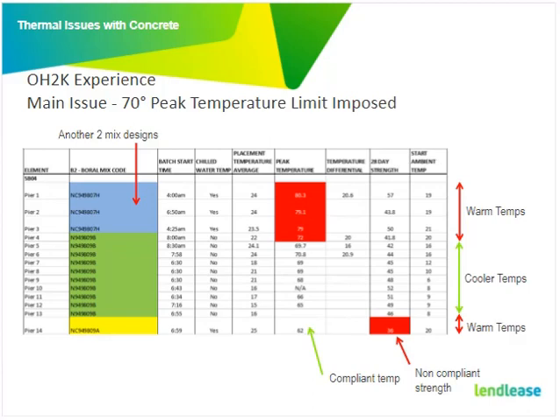What that does is slow down the chemical reactions a bit, and I suppose people in this room will be able to explain it better than me. It does reduce your peak temperatures, but what you end up with is a reduction in the 28-day compressive strength. So there's one way to control peak temperature, but then you've got another non-conformance. You're just chasing your tail. I know in South Australia there are issues with putting slag in the mix because it adjusts, not the sorptivity, but I think the permeability ratios or something. So again, you're putting slag in the mix and then dealing with another issue.